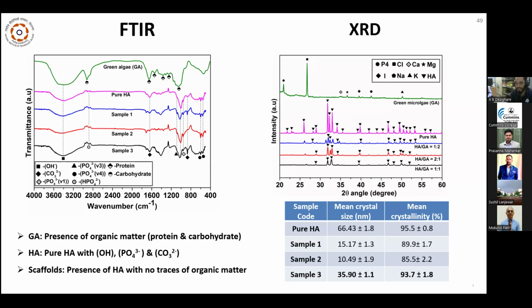Then an XRD test is performed to observe the different phases, and it is observed that compared to pure hydroxyapatite, the intensity is lower. Basically, it becomes a little bit amorphous compared to pure hydroxyapatite. But in all the cases, highly crystalline samples are prepared, where the crystallite size and crystallinity are observed to be higher for sample 3, which is 35.9 nanometers and a crystallinity of almost 93.7 percent.